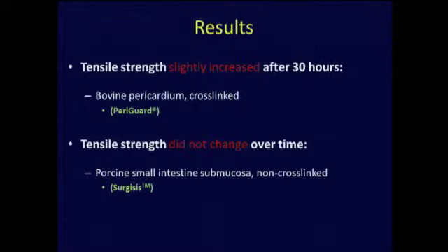Similarly, tensile strengths increased. One of the interesting things was that tensile strength increased for one of the grafts at 30 hours. This is a bovine pericardium that's cross-linked, and the etiology of that is not understood. The tensile strength did not change over time for the small intestinal submucosa, but was at the lowest level of all the grafts and was immeasurable after 6 hours of exposure.